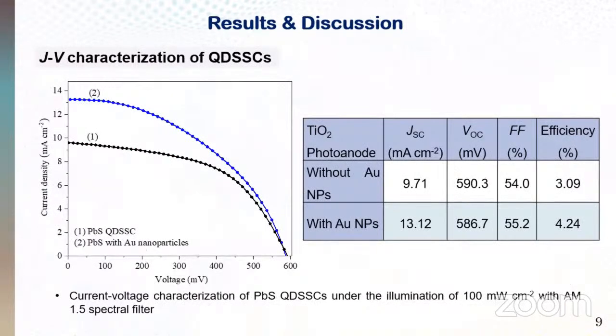This figure shows the current voltage characterization of TiO2 PbS photoanodes with and without gold nanoparticles under simulated light conditions. Gold nanoparticle incorporated PbS quantum dot sensitized solar cells show improved photovoltaic performance compared to the control device. This is evidently due to the enhanced photocurrent in the QDSSC with gold nanoparticles compared to the device without gold nanoparticles under similar fabrication and light conditions, caused by the LSPR effect of gold nanoparticles.